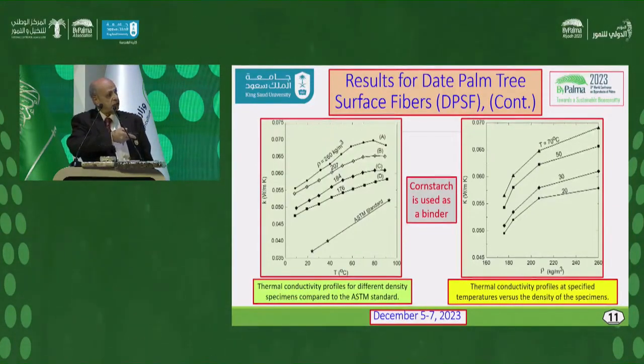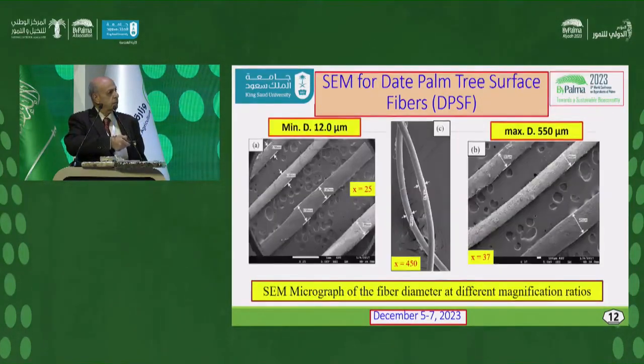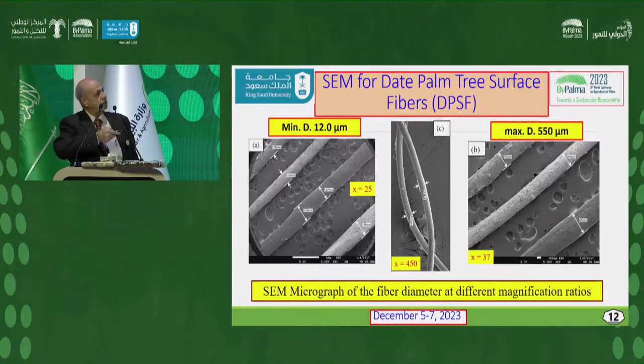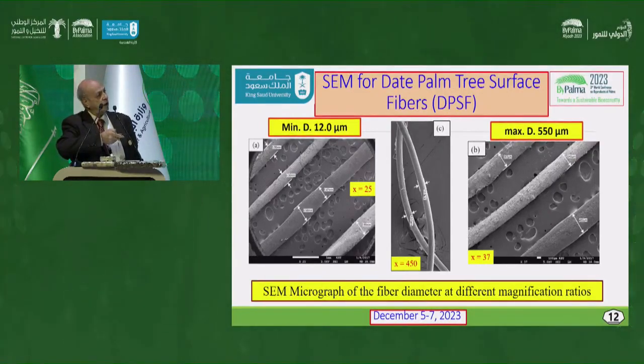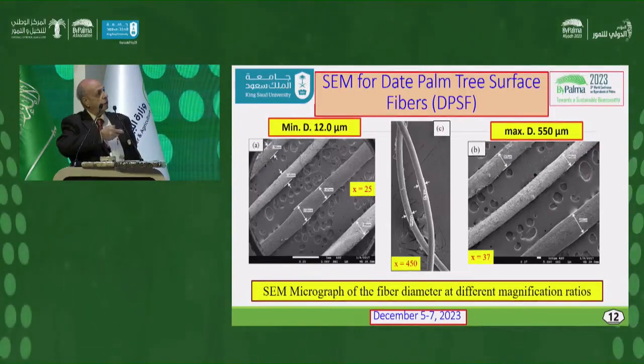And this is the variation of the thermal conductivity with the density at various temperatures. Of course, it increases as the temperature increases, and for a fixed temperature, it increases as the density increases. This is the SEM of the surface fiber, with a diameter between 12 micrometers and 550 micrometers for palm tree surface fibers.